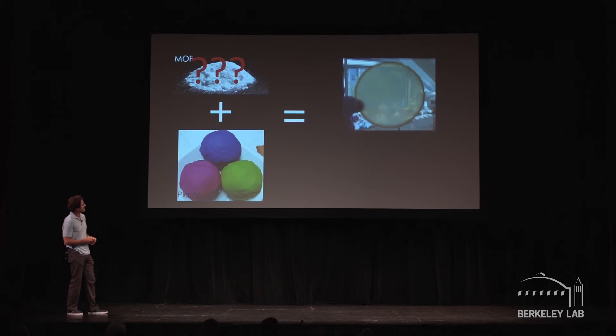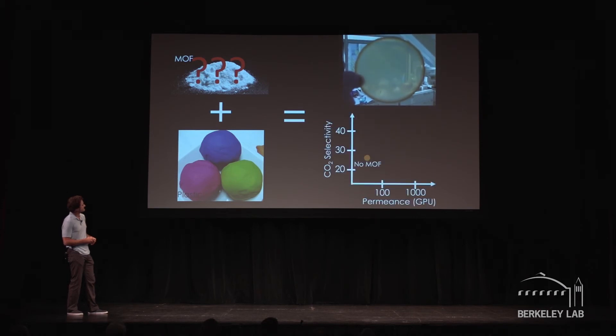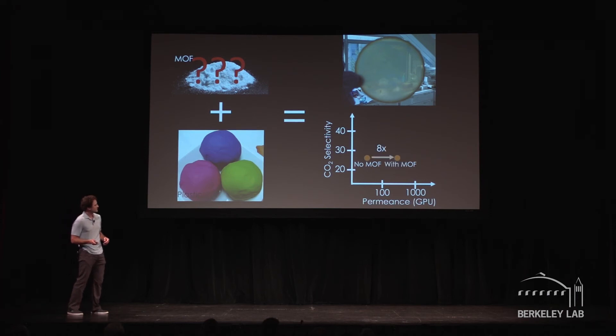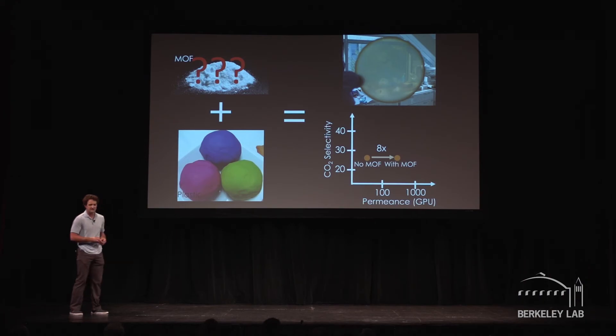With this membrane, you can do something very, very interesting. You can still be very selective for grabbing CO2, but you can get a lot more going through. We've done basically an eight-fold enhancement just by putting the MOFs into a standard, commercial-ready membrane.